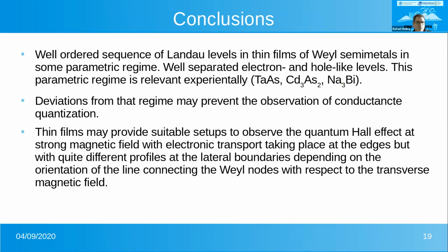As a conclusion, we have a well-ordered sequence of Landau levels in thin films of Weyl semimetals, but only in some parametric regimes, where we have well-separated electron- and hole-like levels. This seems to be relevant experimentally for many materials, but in fact, the parameters are quite close to the change of regime, so deviations may prevent the observation of conductance quantization. And as we increase the magnetic field, we can move to the Weyl cone regime. That's what I wanted to tell you about Weyl semimetals.